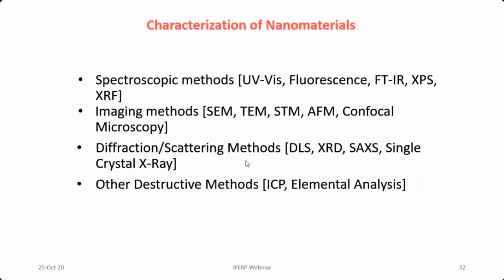Then FTIR. FTIR is very good in terms of finding out the metal capped with different types of materials, like bare metal compared to the capped nanoparticles. You can identify easily using FTIR, and those capping materials can be identified. Any chemistry done on those capping materials, like you are attaching certain kinds of probe molecules, all those things can also be checked with FTIR. So it is a very basic yet affordable and very good technique to check some of the chemistries of metal nanoparticles.